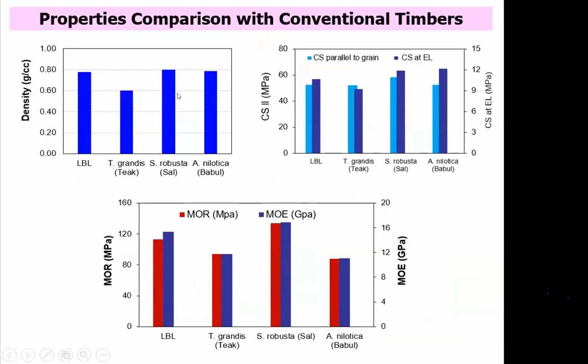These are some of the properties of the bamboo lumber, which are compared with our primary timbers like teak, sal, and this is babul, Acacia nilotica. So we can see that most of the properties are either comparable or better than these primary timbers. This LBL has a density of around 0.8, and the teak has 0.6 density, and Shorea robusta 0.8, and Acacia nilotica also 0.8.